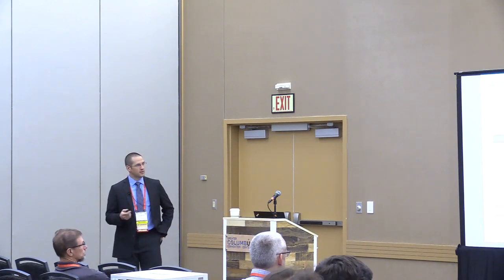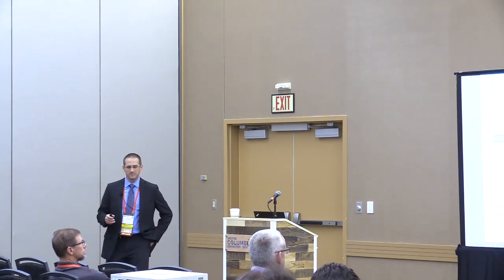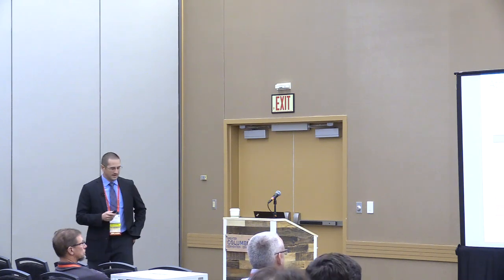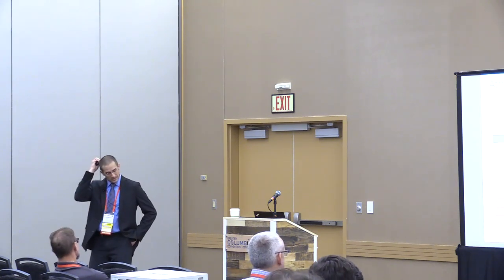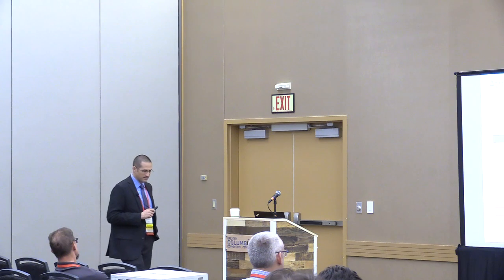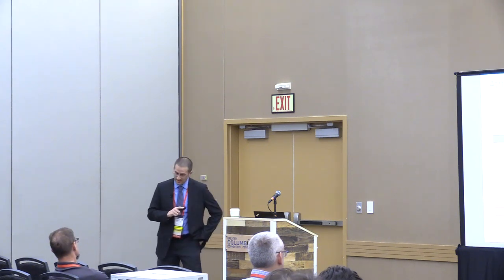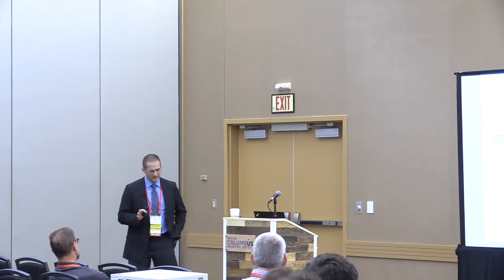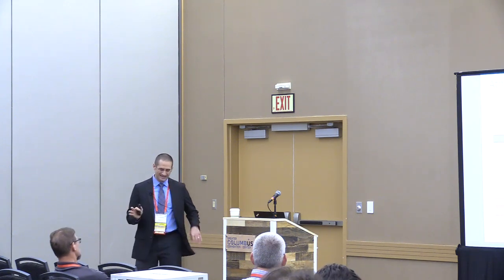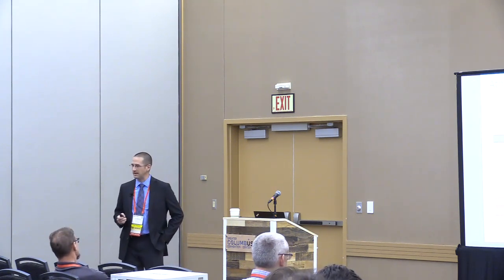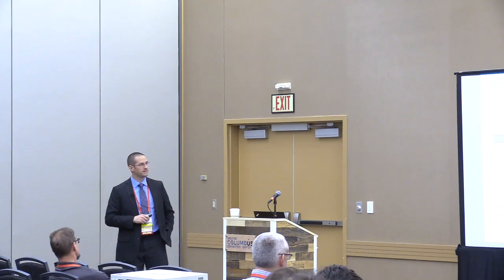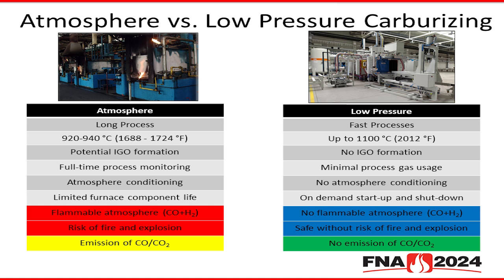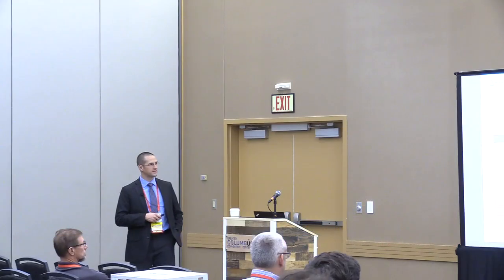On the contrary, with the low pressure process, we can typically tune it to be a somewhat faster process. Now, I say up to 1100 C. I want to footnote that with the fact that most of the normal carburizing steels, which this may not necessarily apply to, we typically would limit to around 980 C just to prevent some extreme grain growth in the process, but we'll come back to that. Because there's no gaseous environment in the furnace, there's no real opportunity for IGO formation, which is a plus to this alternative.